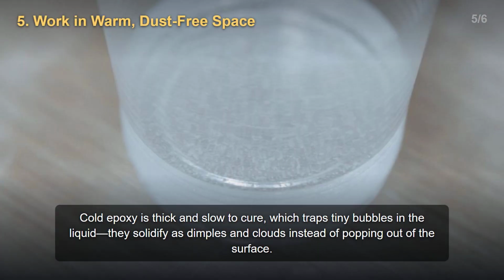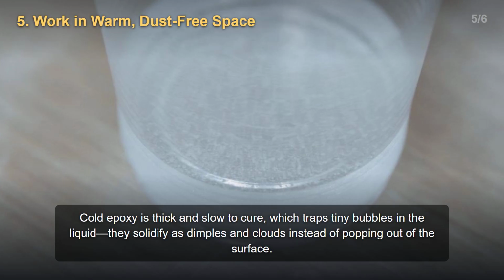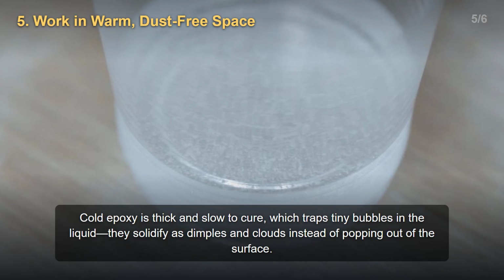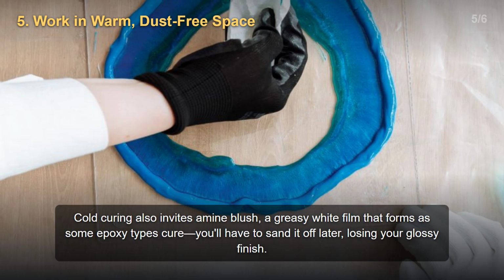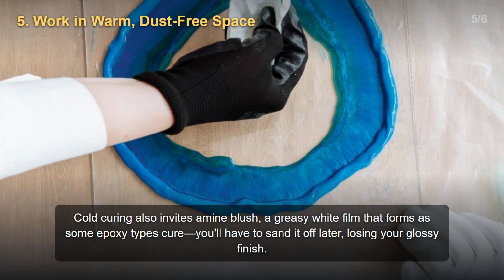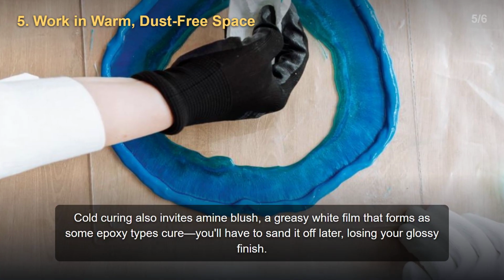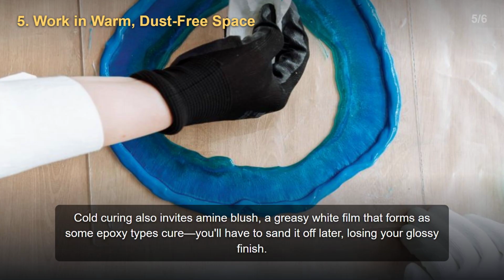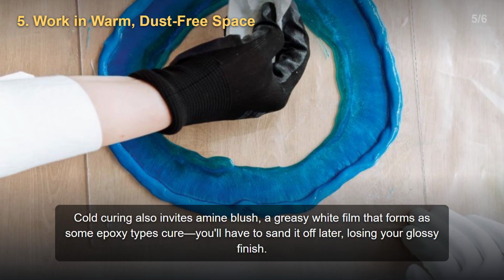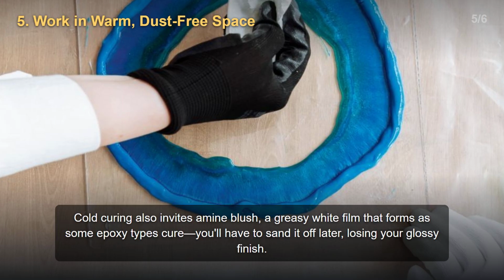Work in a warm, dust-free space. Cold epoxy is thick and slow to cure, which traps tiny bubbles in the liquid. They solidify as dimples and clouds instead of popping out of the surface. Cold curing also invites amine blush, a greasy white film that forms as some epoxy types cure. You'll have to sand it off later, losing your glossy finish.